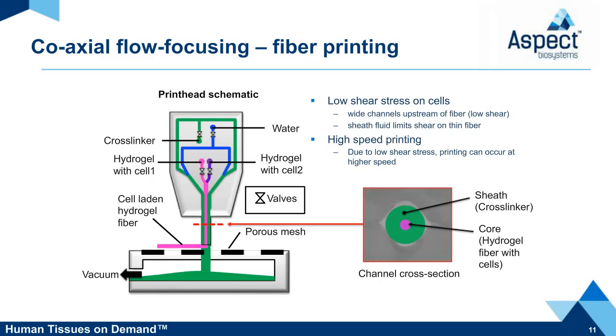Right before deposition, a cross-linking fluid is introduced co-axially, and this rapidly cross-links the bioink to generate a solid fiber that is patterned in 3D. On the right-hand side here, you can see a cross-section of the fiber with that cross-linking sheath fluid surrounding it. Excess cross-linking solution is removed by printing on a porous substrate and applying a vacuum.